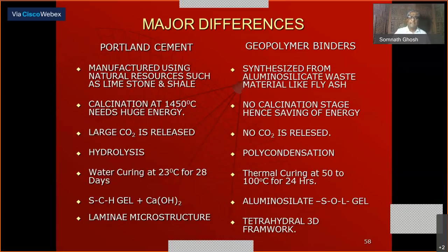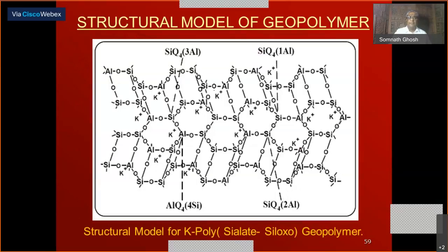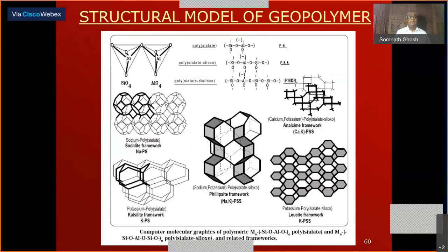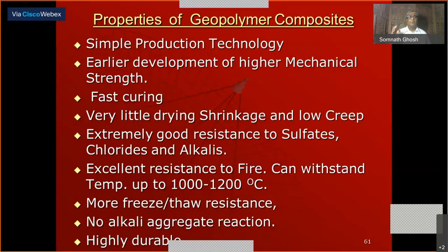Now you see, these are the polymeric structures. These are different things, I am not going into them. Someday we'll discuss. Now, you see the simple production technology and earlier development of higher mechanical strength, fast curing, because if you go for heat curing, you will do it. That, of course, you can do for concrete also. Very little drying shrinkage, low creep, extremely good resistance to sulfate, chloride, alkalis. When you are adding fly ash, the total alkali, whatever the calcium hydroxide, is consumed. So there is no presence of alkali, so alkali cannot do any harm to the concrete.